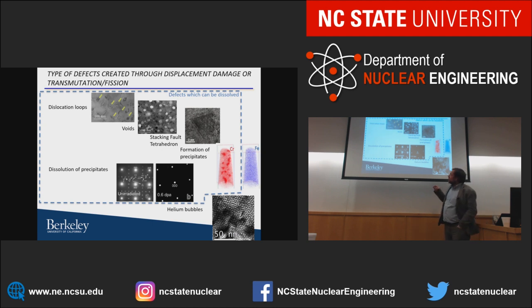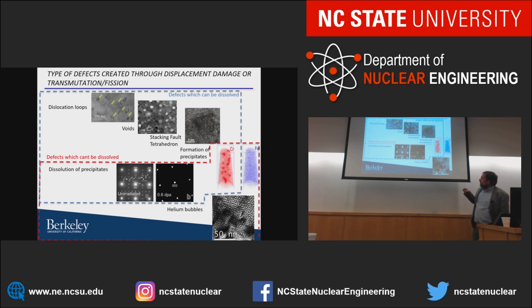So all these defects, dislocation loops, to some degree voids, precipitates, and even, of course, precipitates we dissolve anyway due to radiation. If I mechanically deform them, I can dissolve them, because the mechanical deformation is dislocations traveling through your material. And if you have dislocation-like features or defects, they can be absorbed in those dislocations. Or we can have features not getting dissolved due to mechanical deformation, which will be helium bubbles, precipitates, and it depends on what kind of precipitates we're talking about. The difference between those two has very different implications for whether a material turns brittle or not, and how it embrittles under radiation, because its deformation mode changes.